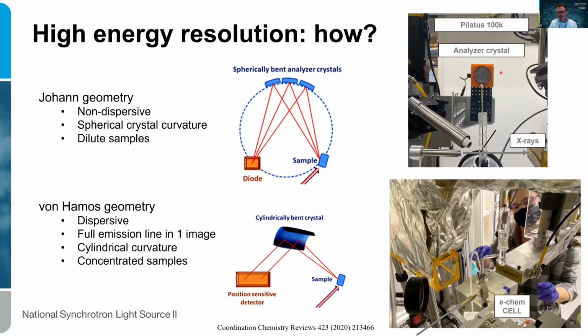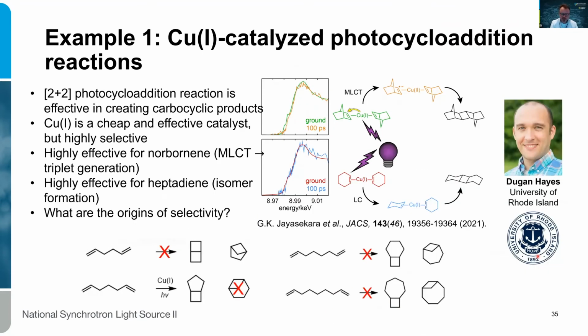So all those preliminary measurements we were doing with just some semblance of the spectrometer, the motorized analyzer crystal, and the detector that's here somewhere. But even with this setup, and obviously with the helium chamber, something that Jerry was talking about in the beginning, we could get very competitive data. It's also compatible with some of the in situ setups, and we are constantly adding new in situ instrumentation to these measurements.